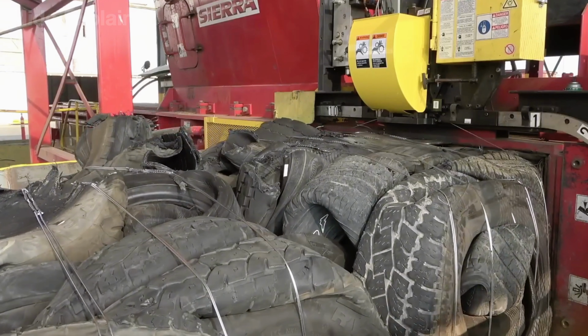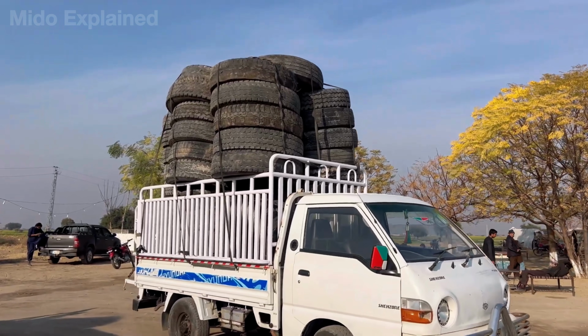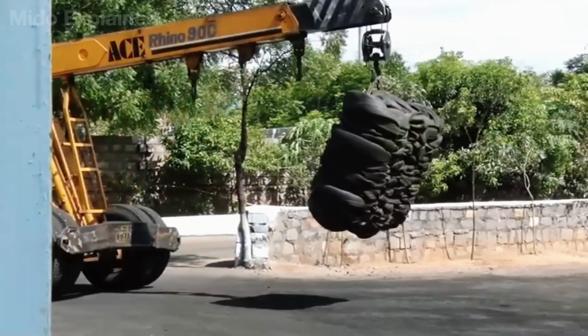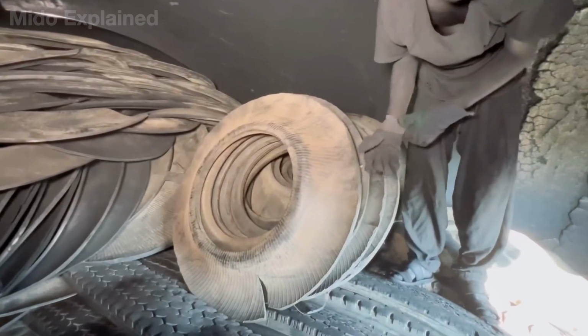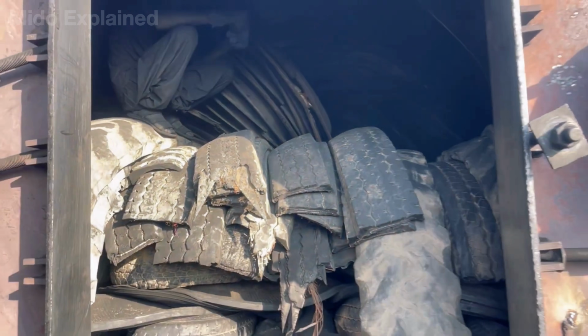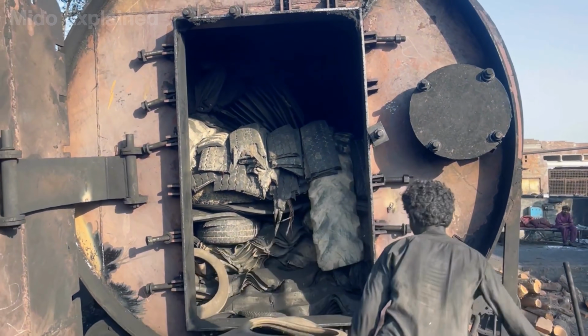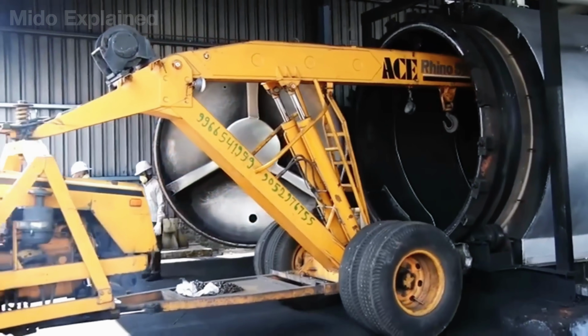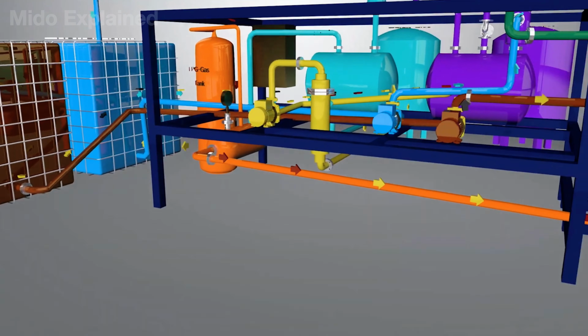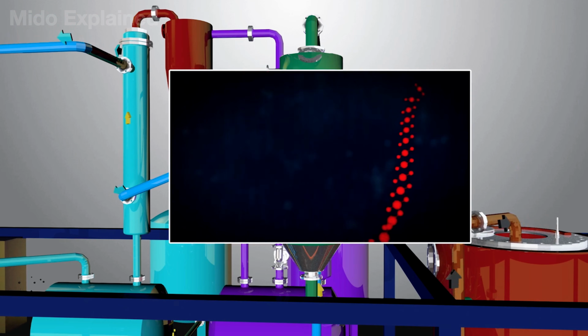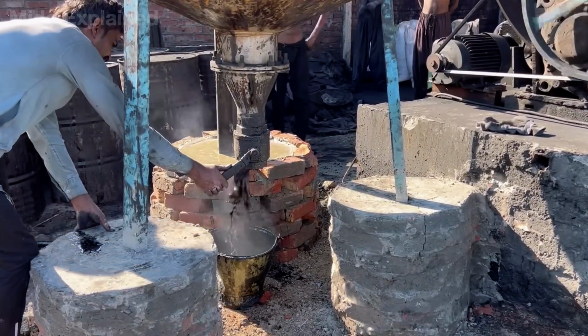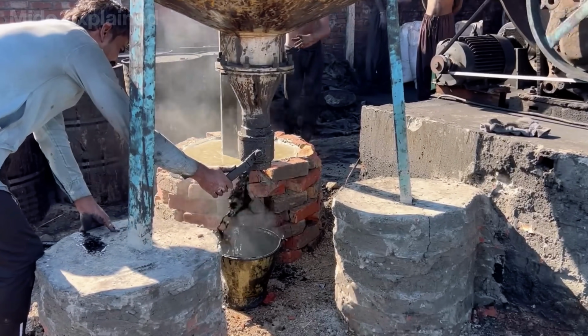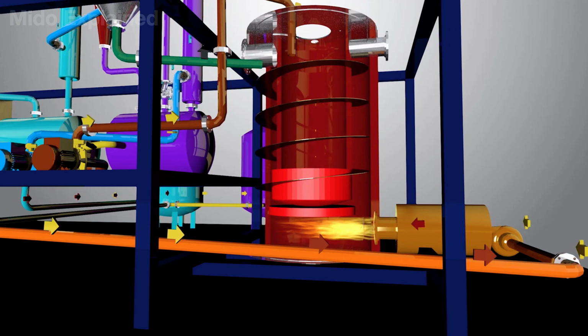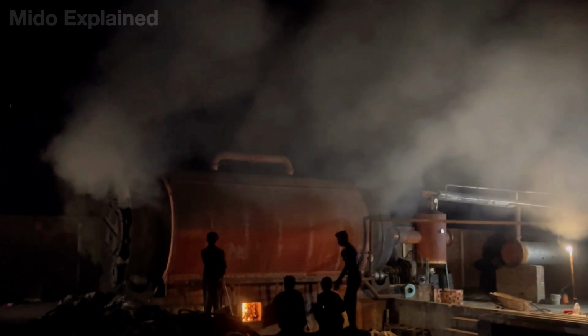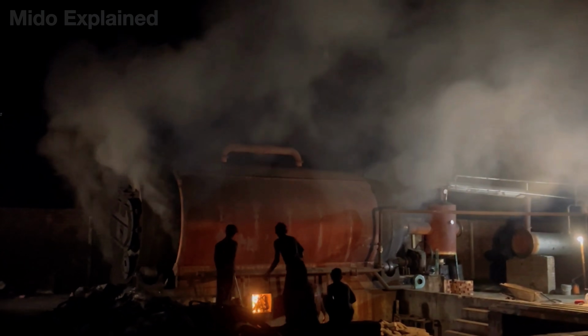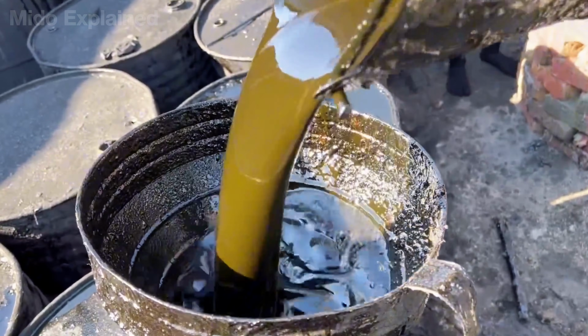Besides mechanical grinding and retreading, pyrolysis is another recycling method that is gaining increasing popularity. Instead of direct incineration, tires are heated in a sealed chamber at approximately 1,000 degrees Fahrenheit in the near absence of oxygen. Under these conditions, the rubber does not burn but decomposes into three main products: pyrolysis oil, gas, and carbon black. On average, 1 ton of waste tires can produce over 100 gallons of oil, which, after refining, can be used as industrial fuel.